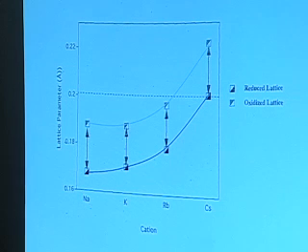And of course, after you do this, you have to go and do the experiment I showed you first to see it in action and actually see the dynamics. Because there is a question. Well, there were a lot of questions. Just because you got this lattice change, do you really think that's happening in the electrochemical cell? But probably the more interesting question is, does this thing expand linearly as the electrons are going out, or is it just sitting there and then at some magic point does it expand? Or what's the relationship between the mechanics here, if you will, and the electrochemistry? And it turns out it's linearly correlated. We know from that experiment.